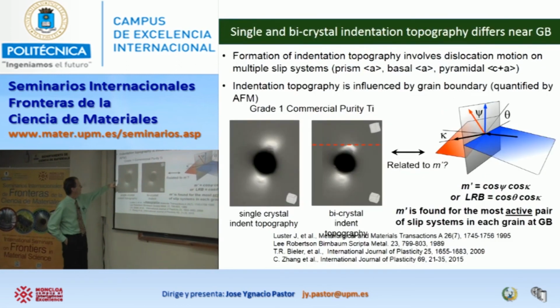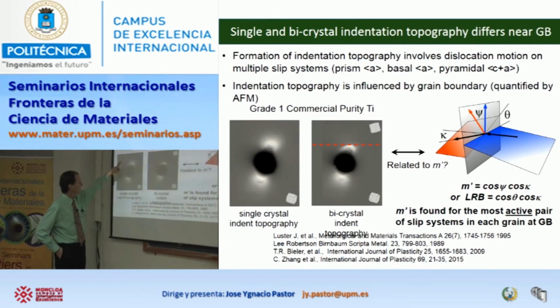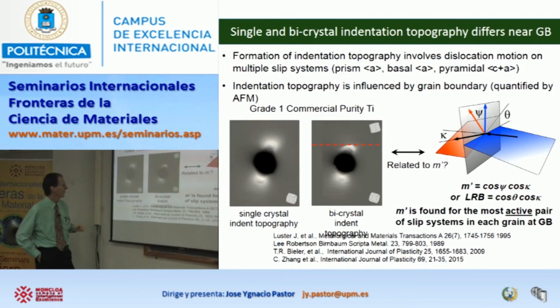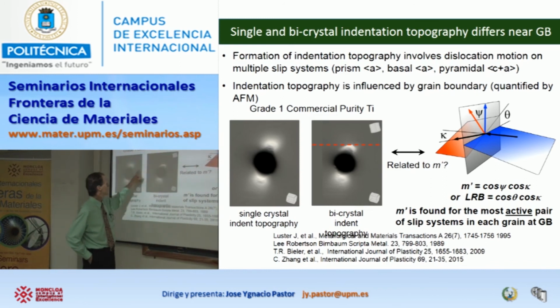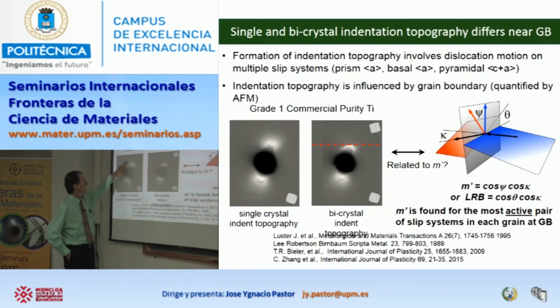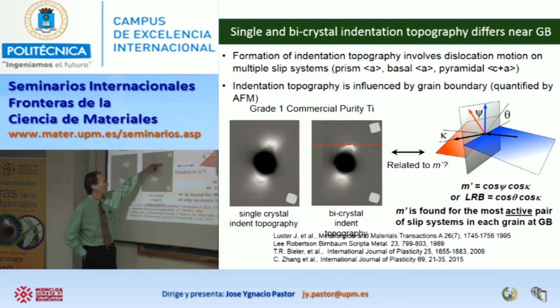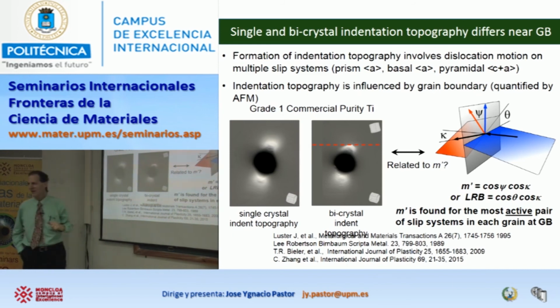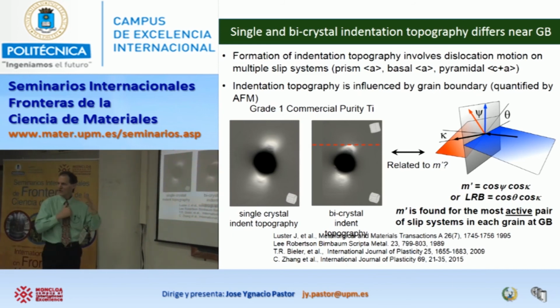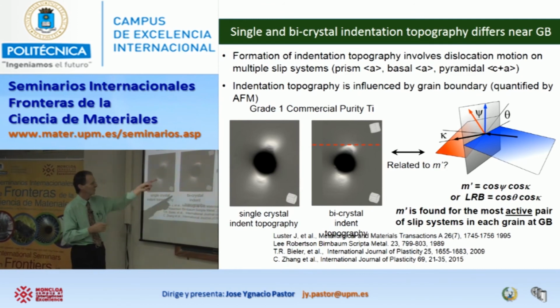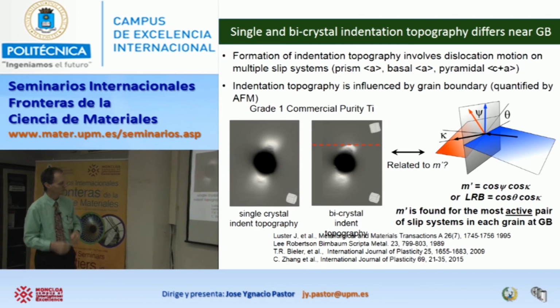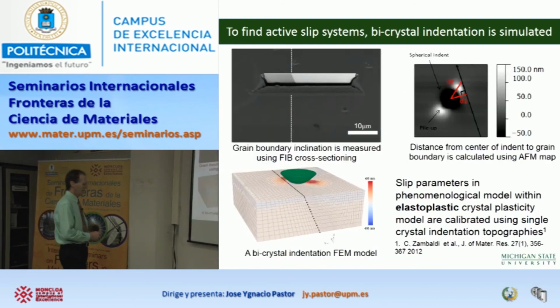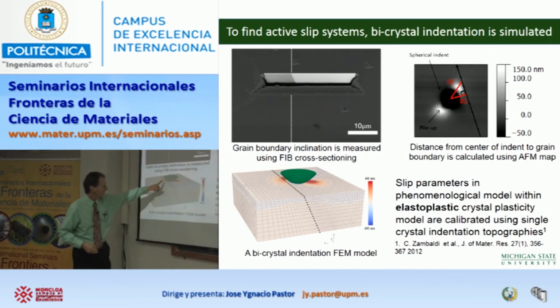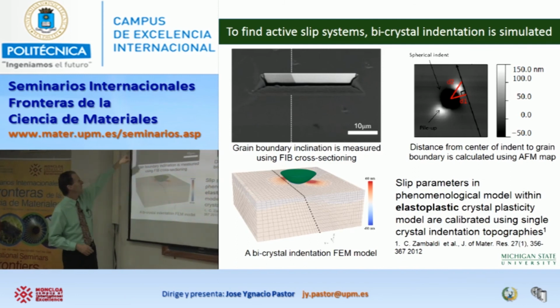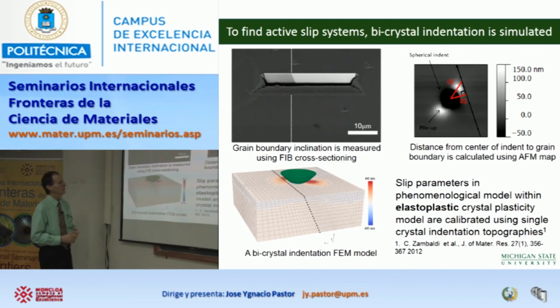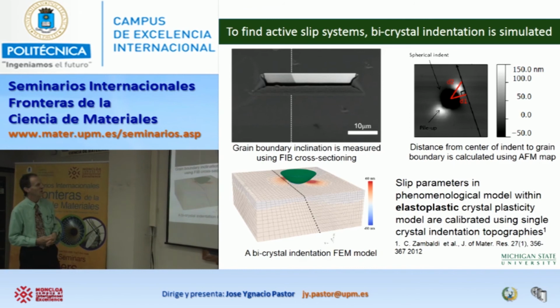And so here's an example of an indent in a single crystal. This is just in the interior of the grain. And here's another indent that's right next to a grain boundary. You can see that the topography that is spread out over here is somewhat abruptly stopped by the grain boundary. So the grain boundary essentially is a block to slip deformation. So the same M prime that I showed you before is what we're using. And the other thing we can do is figure out what the actual grain boundary plane looks like by doing a FIB, focused ion beam, slice at the grain boundary, and we can measure the inclination of the grain boundary.